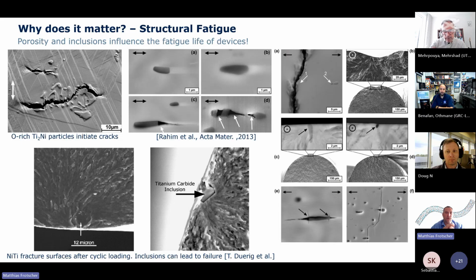At the bottom right, you can see two fracture surfaces of nitinol wires subjected to rotary bending fatigue, where the wire is bent into an arc and rotated until fracture. Inclusions on or close to the surface can act as stress raisers and can initiate cracks.